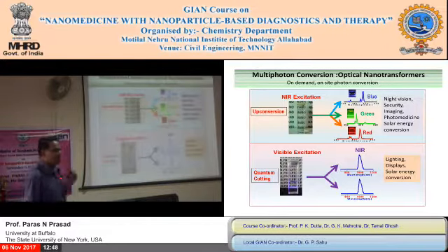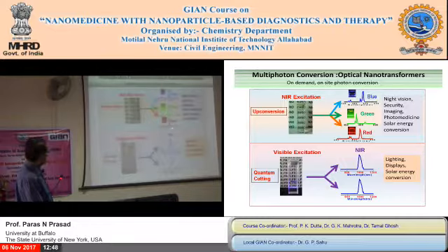If it has erbium ion, we generally use a fluoride lattice. Okay, so the erbium ion will give you green or red color upconversion, as you see this streak. As soon as you shine light through here, you will see a green, red streak, or another formulation, a green streak, or another formulation, blue, if it is thulium. So 980 IR to blue color.